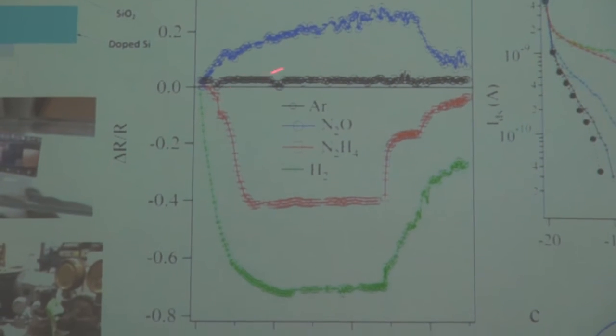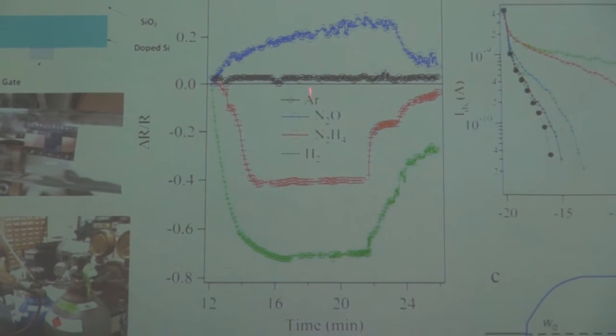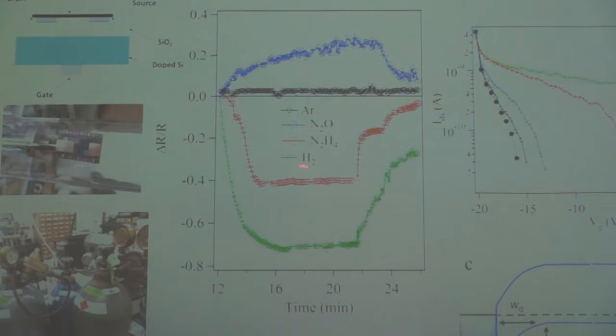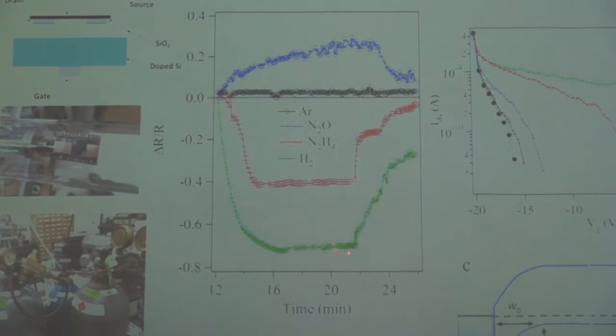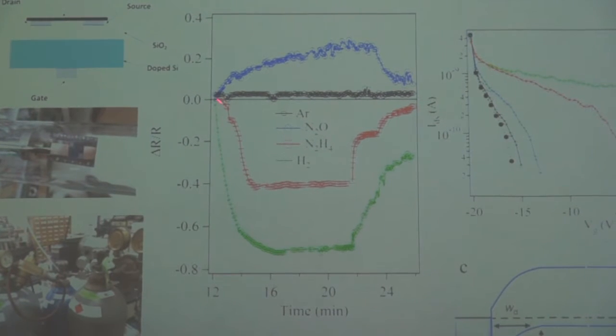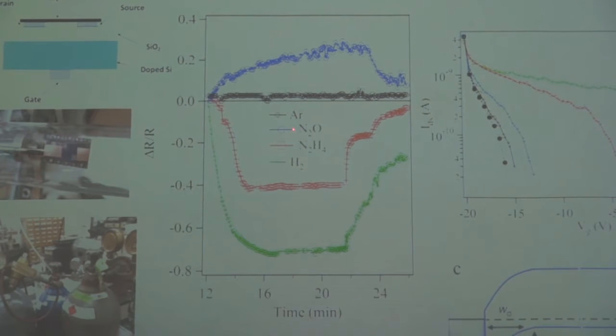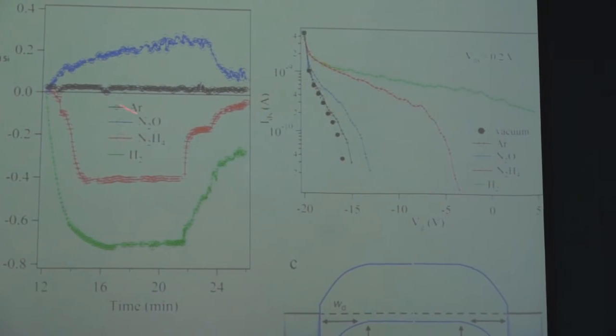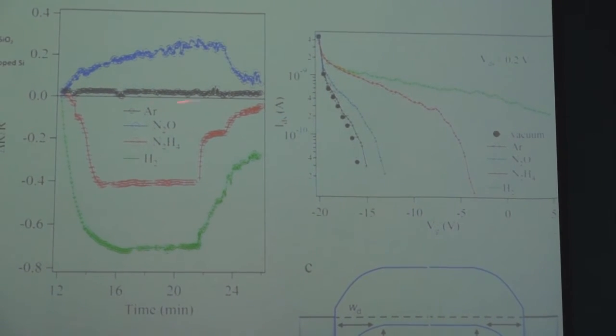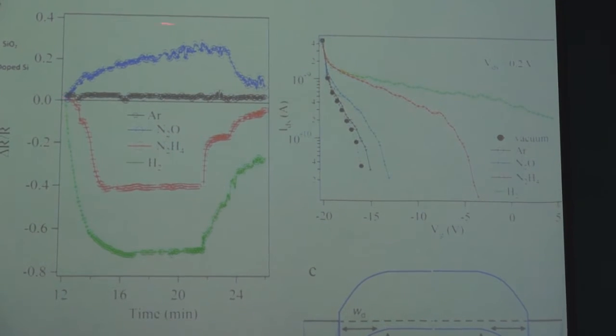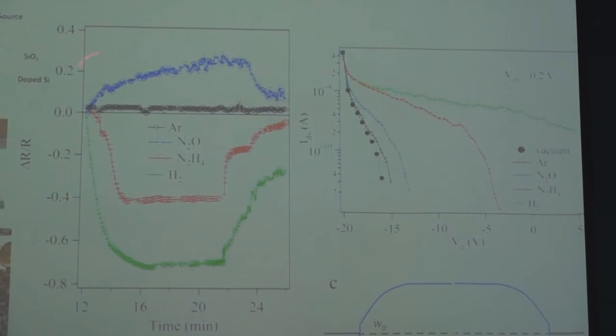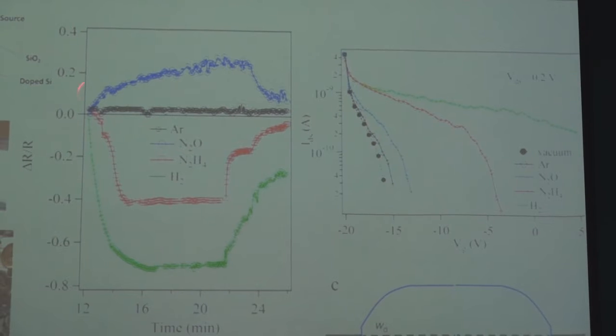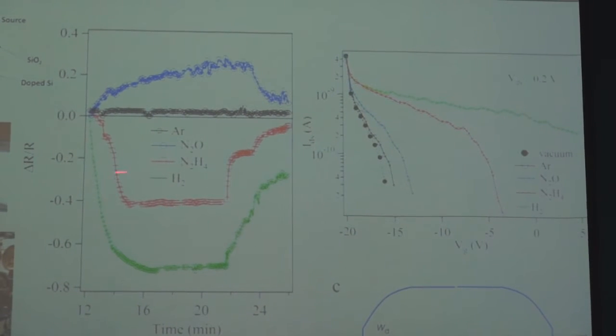Then we also look at sensor properties. You can see how resistance changes for different gases. For hydrogen, resistance is decreasing. For argon, it's almost no change. For nitrous oxide, they show increasing resistance. So we know these are good reducing agents, and this is a good oxidizing agent.